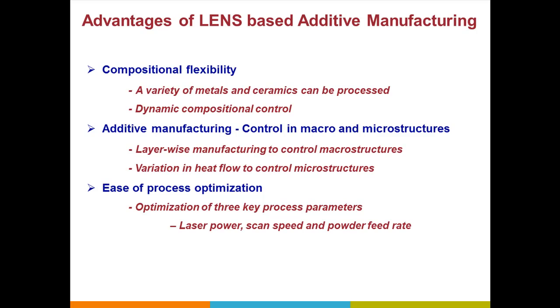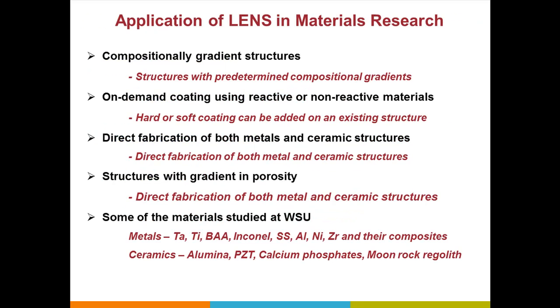You need to imagine the powder feed rate this way: powder is a cold thing that we're putting into the hot zone. So if we increase the powder feed rate, we're basically slowing down the heat input. If we decrease the powder feed rate, we can keep the heat longer at that focal point. So by tailoring these 3 parameters, we can work with almost any material quite quickly to see if we can use the LENS process to manufacture parts with it or not.